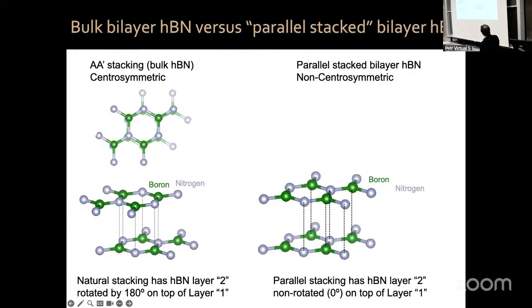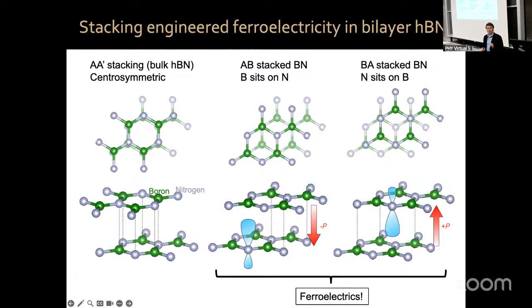So we have 0 degrees, layer 2 on top of layer 1. This is something very uncomfortable. Boron doesn't want to be on top of boron, and nitrogen on top of nitrogen. So what the system does is it shifts into one of two configurations: either an AB stacking configuration where the boron sits on top of the nitrogen, or a BA stacking configuration where the nitrogen sits on top of boron.